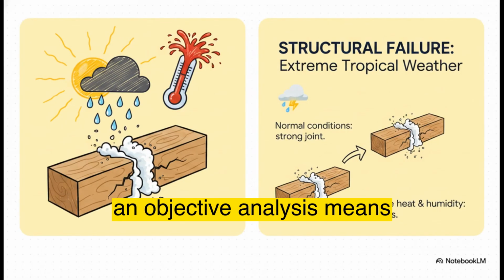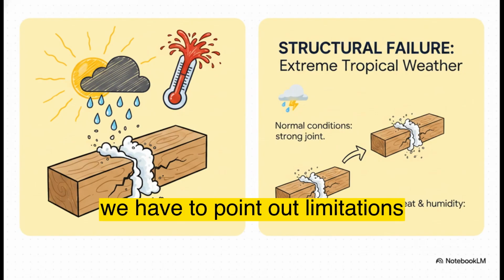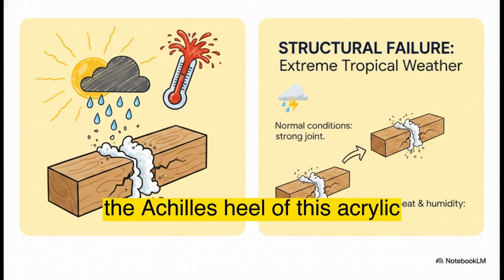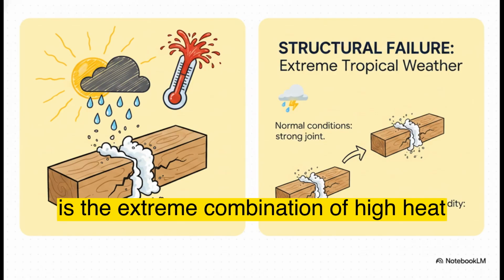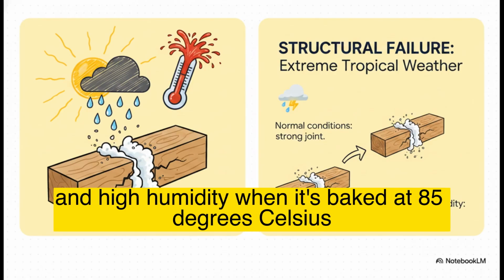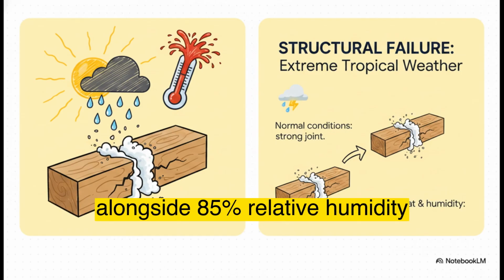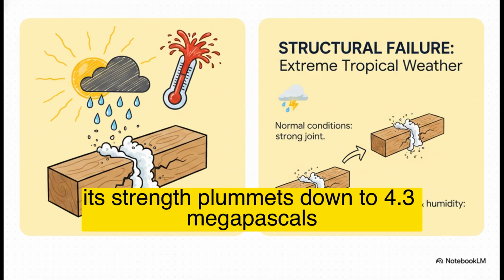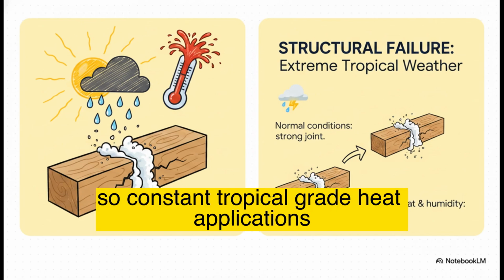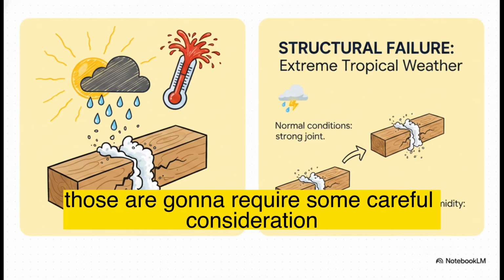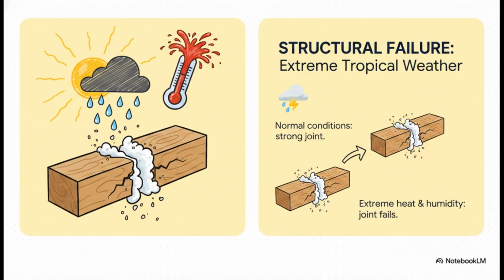But an objective analysis means we have to point out limitations. The Achilles heel of this acrylic is the extreme combination of high heat and high humidity. When it's baked at 85 degrees Celsius alongside 85% relative humidity, its strength plummets down to 4.3 megapascals. So constant tropical-grade heat applications are going to require some careful consideration.